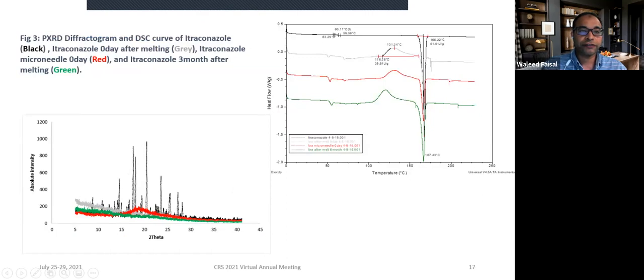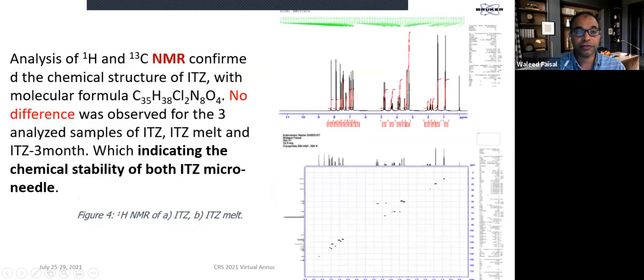When we look at the XRD diffractogram and the DSC curves, we can see the melting of the itraconazole, and we can see the glassy amorphous structure of the melt, which is stable over 3 months as an amorphous structure.